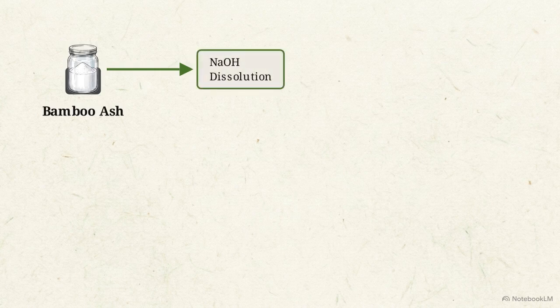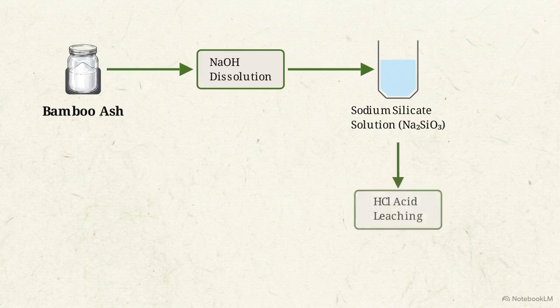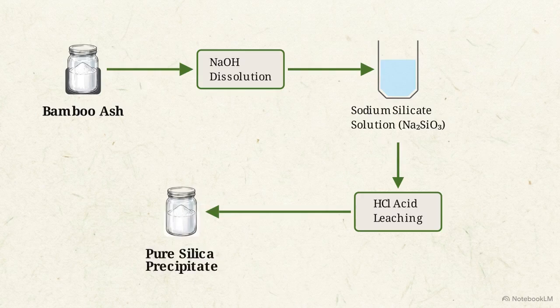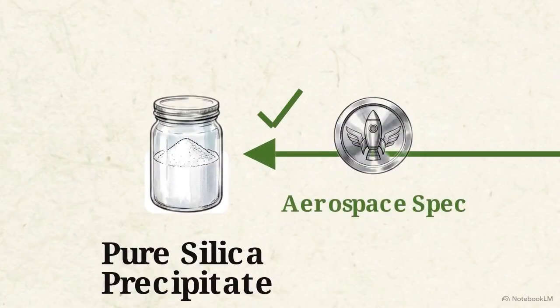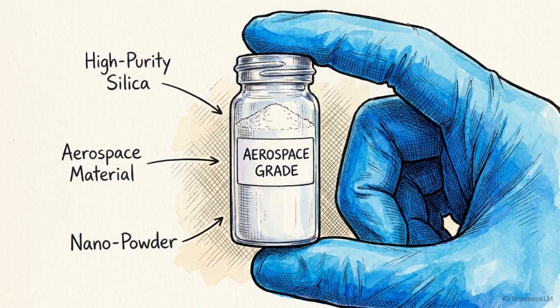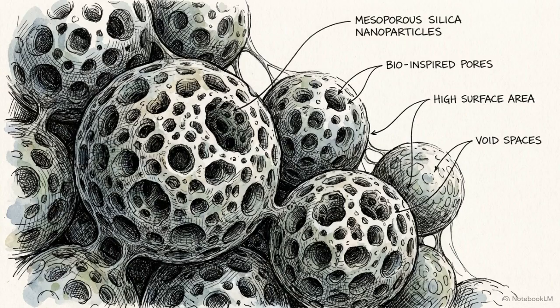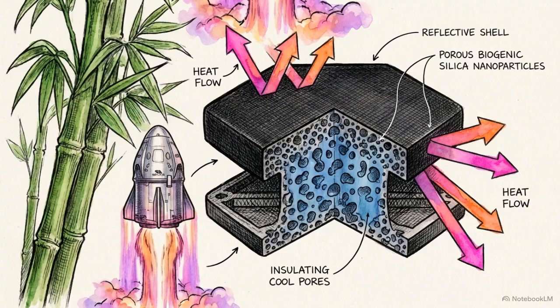Beyond pure chemistry, the plant-derived material has a unique physical structure. The biogenic silica nanoparticles are natively mesoporous. These microscopic void spaces act as built-in insulation. The trapped air drives the thermal conductivity down to less than 0.1 watts per meter Kelvin, essential for resisting re-entry plasma. This natural nanostructured architecture results in a material that is structurally optimized for thermal insulation per unit of mass, surpassing the performance of denser mineral fibers.